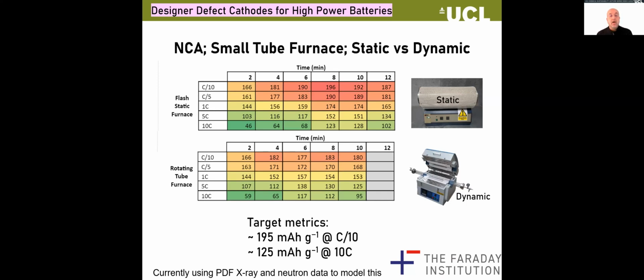One of the things we are currently working on in our Faraday project, which is a seed project that lasts a year, is the static furnace. So this is data from the static furnace, at different C rates. At 10C, 128 milliamp hours per gram in a 6-minute charge or discharge for an NCA material is 10% better than the commercial NCA material that our industry collaborators can get. 10% is a big deal at 10C. So now our job is to take it from the static to the small rotating to the large. So we're on that journey.